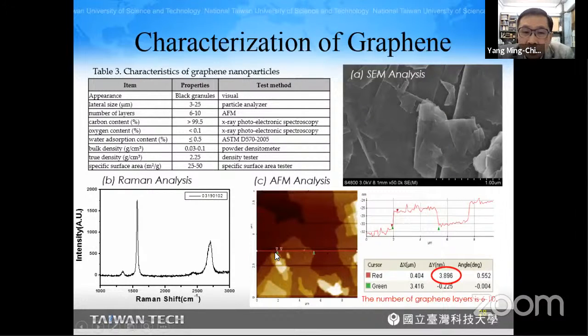So we measured the thickness, the height of these flakes here. And we can see the profile observed between these two green dots. This shows that the thickness is 3.896 nanometers, which is equivalent to a graphene layer of 6 to 10.